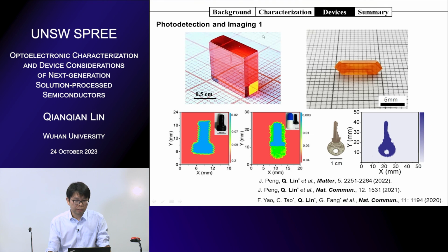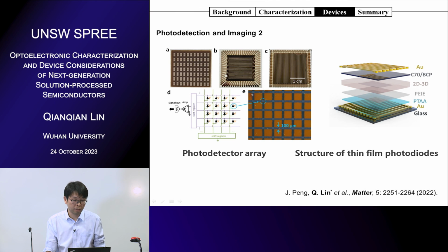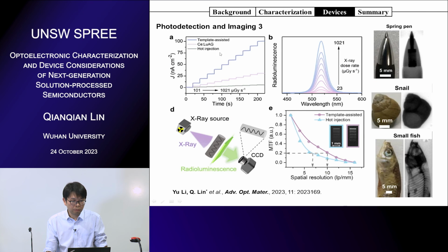The other thing we are doing in my group is imaging. So we use perovskite single crystals, and we do some X-ray imaging in my lab. And this is a single pixel device, and we just move the device in X and Y, and we can scan the image. And the second method is to fabricate arrays. Technically it's more difficult, but for real application it's easier, I think. So we fabricated more than 1,000 pixels in my lab, and we also do the imaging work as well. And we use scintillators and combine them with a commercial CCD. We can also get very clear X-ray images from the perovskite scintillators.